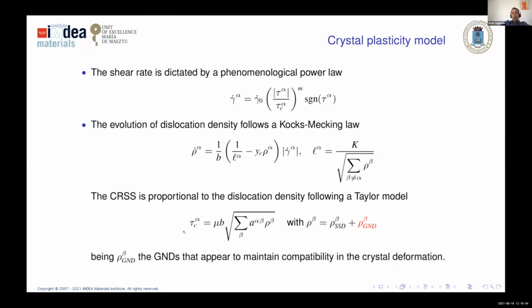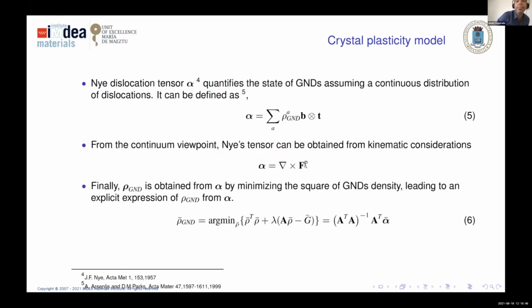This is the evolution of this internal variable, and then the critical resolved shear stress is directly given by the Taylor model, where it is the shear modulus, the Burgers vector, and the sum of the dislocation densities premultiplied by factors that account for the different junctions, that is, the different types of latent hardening from some systems to others. So instead of using the full dislocation density like in the original Kocks-Mecking law, we split it into statistically stored and geometrically necessary dislocations. The statistically stored follow this equation, but the GNDs evolve through a kinematic restriction, as I told you.